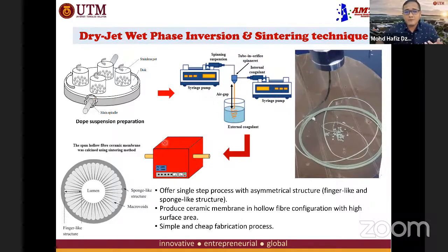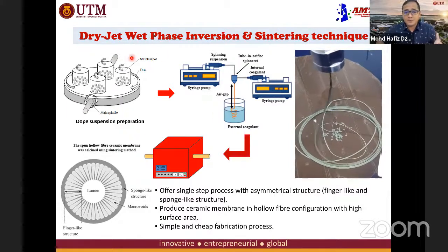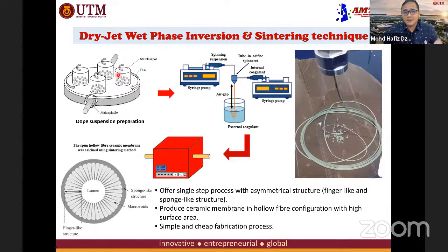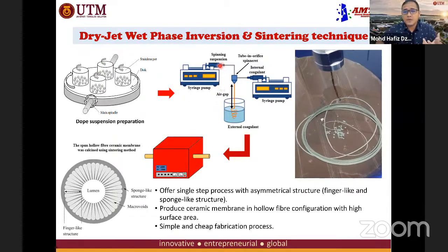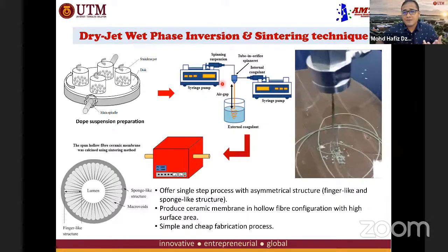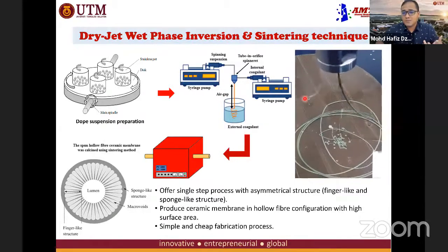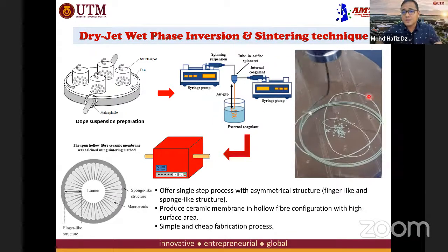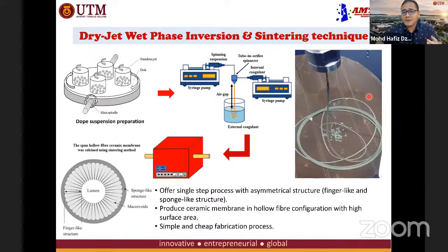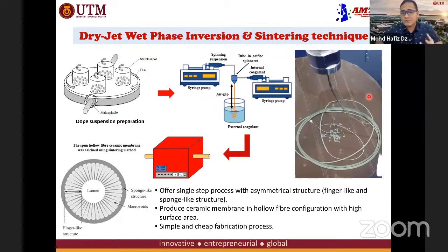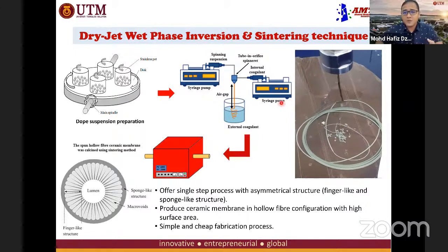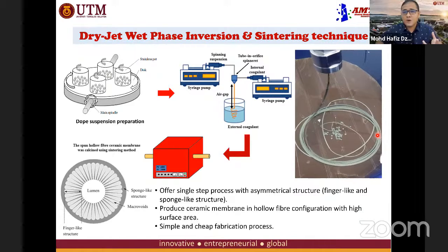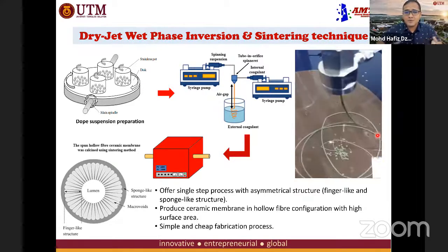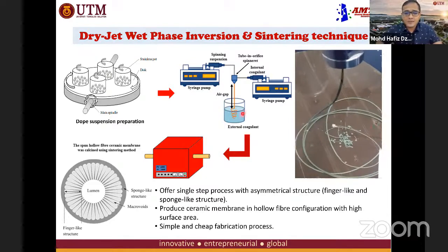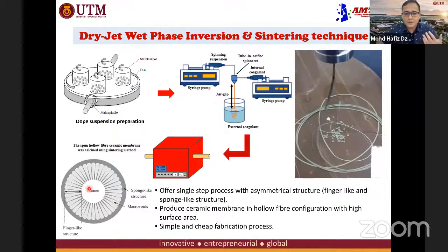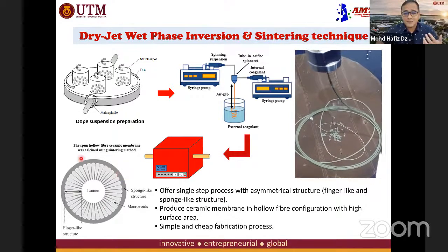So by using this technique, the first step is to prepare the dope suspension. And after you get the suspension, you extrude it through the spinneret using a syringe pump, and it travels some air gap before it reaches the coagulation bath. Okay, the external coagulant, normally we use water. So this is the place where the solidification process from liquid to solid will happen. Okay, so because of this process, this is what we call the solvent-non-solvent exchange that leads to the solidification process we call phase inversion. This phase inversion normally can produce an asymmetric structure in a single step.